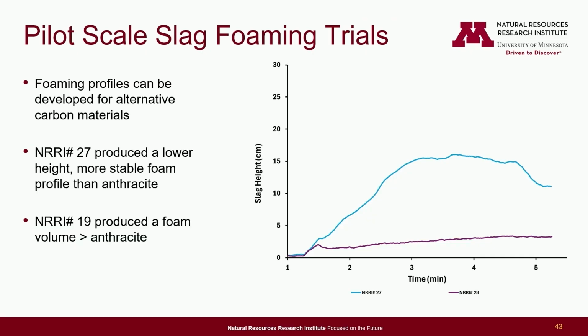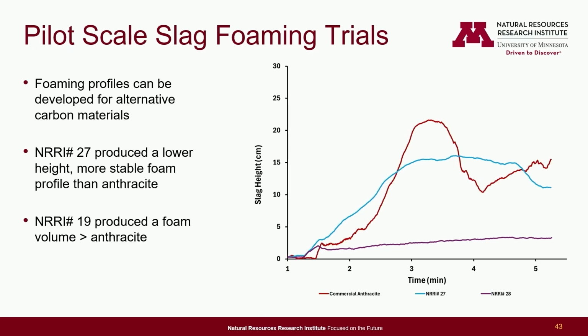Just a big bummer. So we can correlate, basically we collect that slag height over time as well. So in the video there's one that performs well, one that doesn't, which correlates to this line. So this foam height grows over time. So we have the slag height on the y-axis, time on the x-axis, and it grows. And then this one, it just kind of hung out and didn't really move that much. So then we have anthracite here in this red line. So it has a different curve. This one's a little bit more of a sustained foaming height, but it doesn't get as high as anthracite.